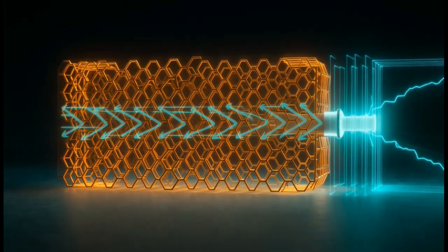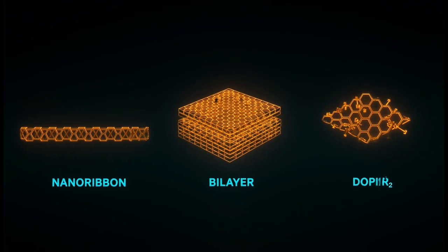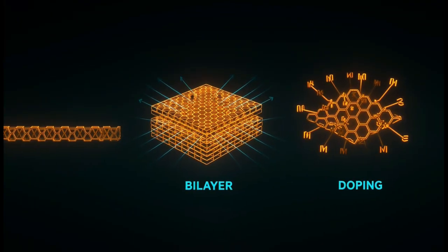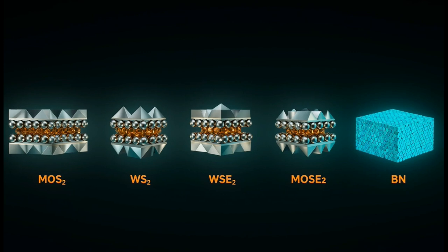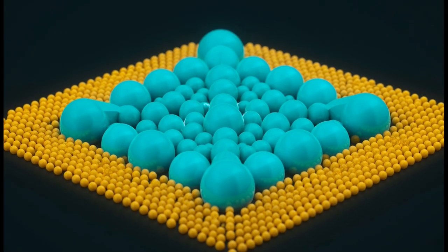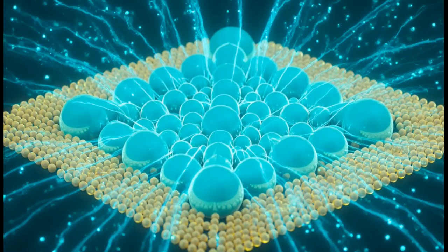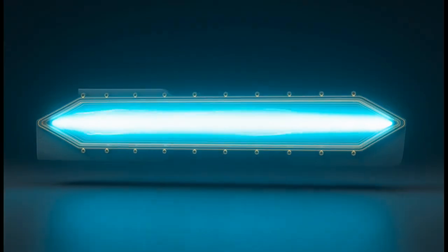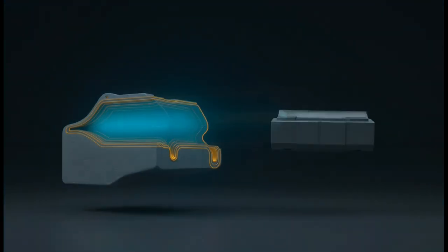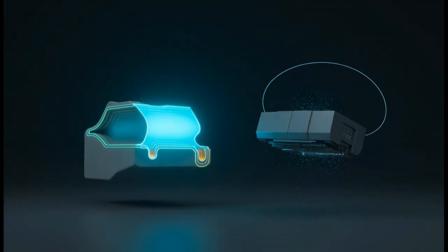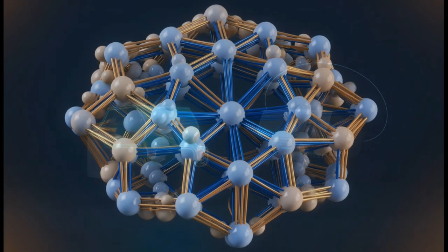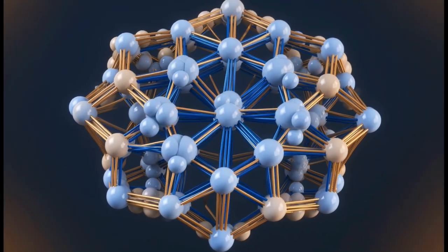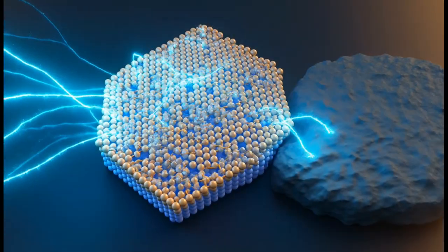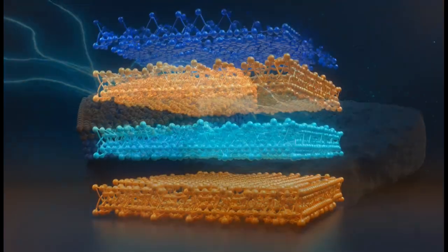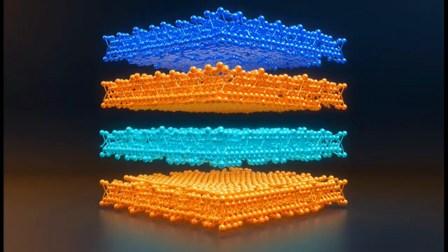But not every carbon nanomaterial makes a good transistor. Graphene itself lacks a band gap and cannot fully turn off. That's where other atom-thin materials come in. MoS2 is just 3 atoms thick and already possesses a direct band gap, ideal for switching. We can also improve graphene by placing it on atomically flat boron nitride, which boosts its electron mobility 50 times.